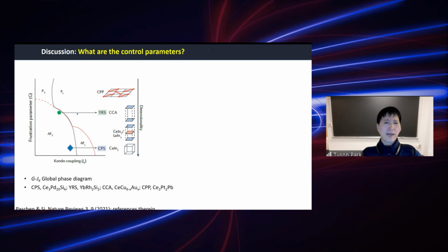Why does it happen? So this global phase diagram by Qimiao et al. provides some hint. This is the x-axis Kondo coupling, the y-axis the frustration parameter. If it's a cubic compound, then the fluctuation of the local moment is small. So when you tune J, you go from antiferromagnetic small to antiferromagnetic large, and then the paramagnetic large Fermi surface phase. On the other hand, in the more two-dimensional case, the fluctuation becomes large, and it actually goes from antiferromagnetic small to paramagnetic large Fermi surface phase.